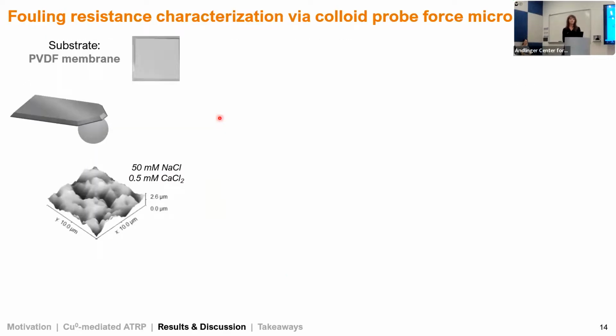Okay, so to characterize fouling resistance, we use colloid probe force microscopy. This is an AFM-based technique in which we use a colloid probe to characterize adhesion forces. We use two probes. The first one is a carboxylic acid functionalized polystyrene particle, which is representative of an organic foulant. The second one is a soft hydrophobic polyethylene particle, which is representative of an oil foulant. And we perform all measurements in a low salinity electrolyte solution.